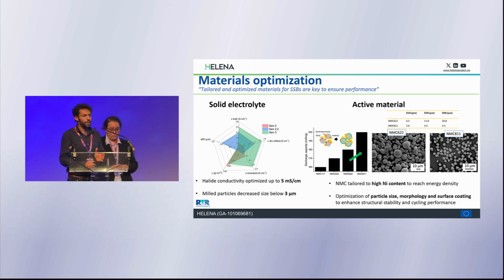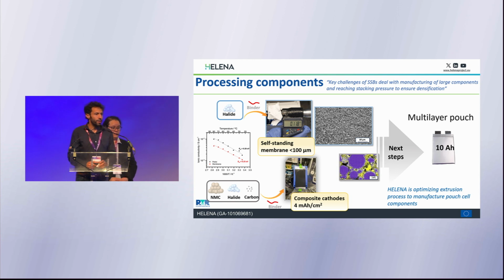On the side of the active materials, same. There's been also good progress on the two families of NMC that were developed with lower and higher nickel content. So here, what I can say is that we now have NMC rich in nickel, which has been optimized in terms of particle size and surface coating that will ensure the performance of the cells. We took those materials to process them into components, and for the moment, we already have cells that are being done at lab scale.